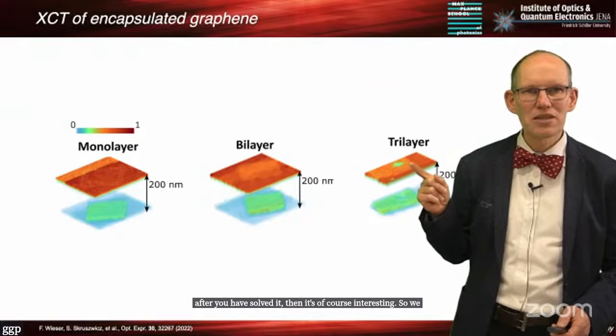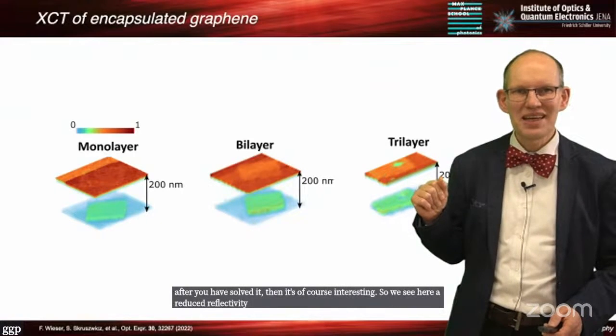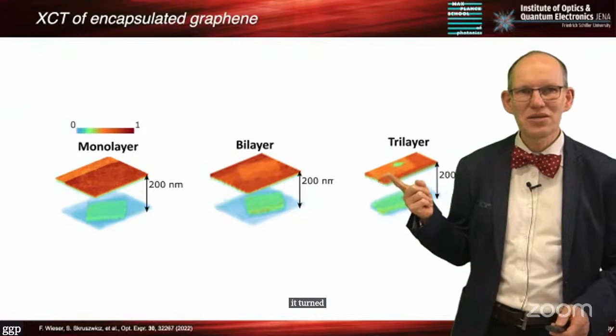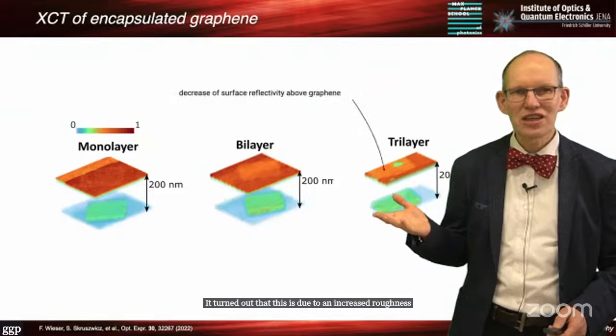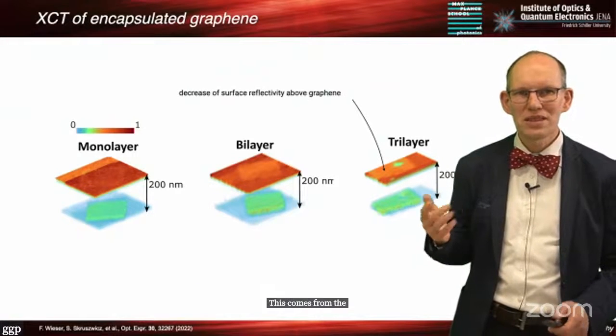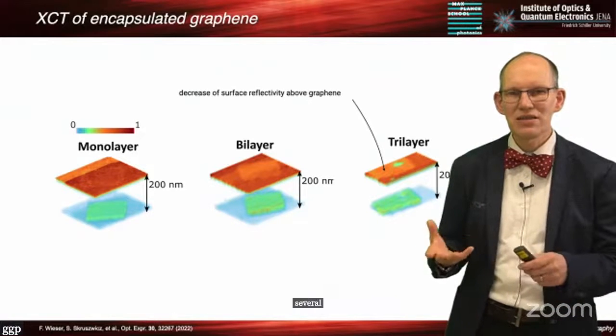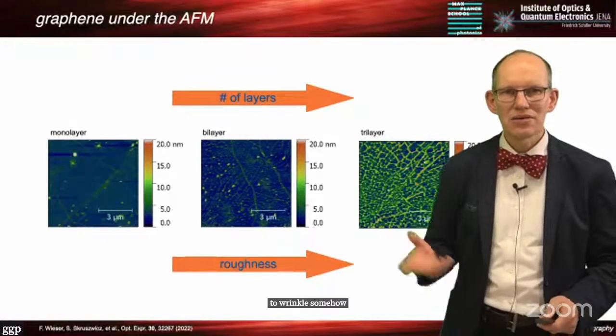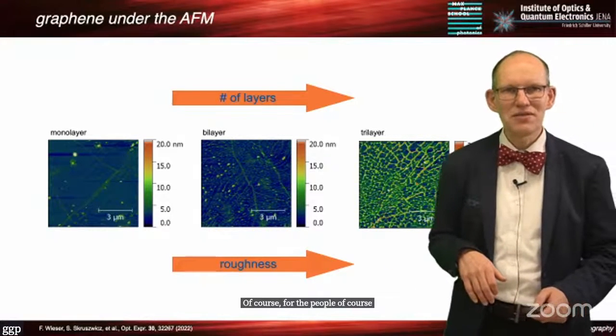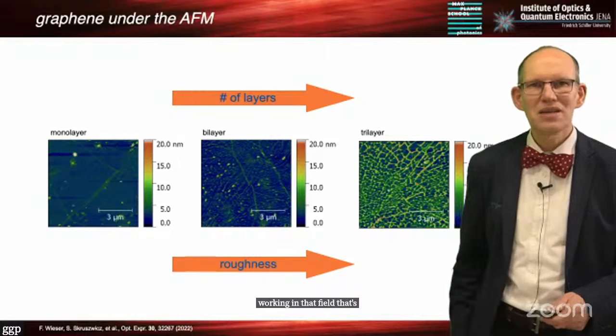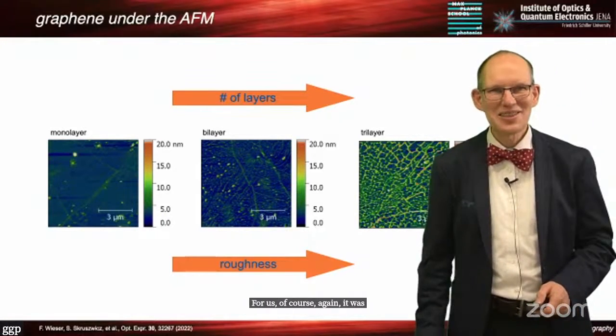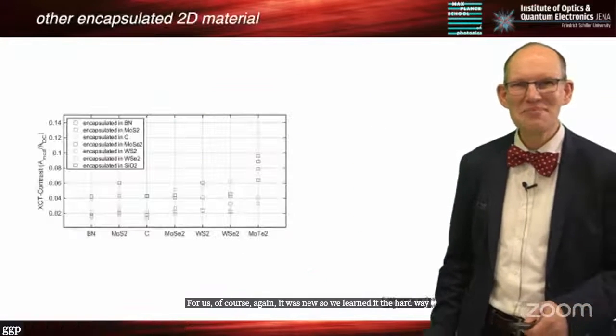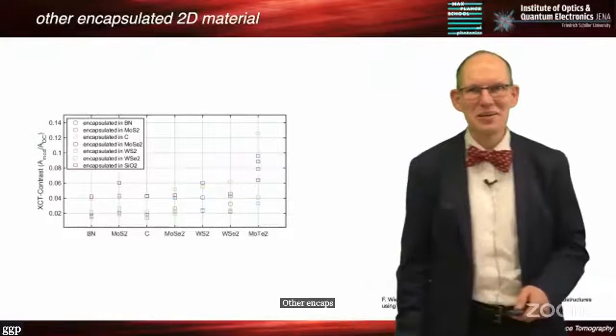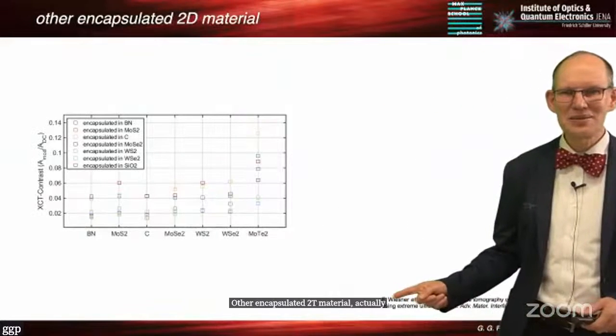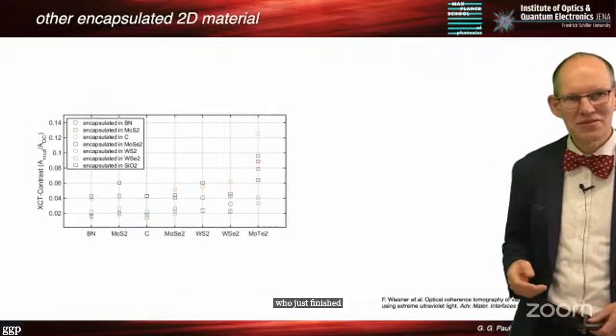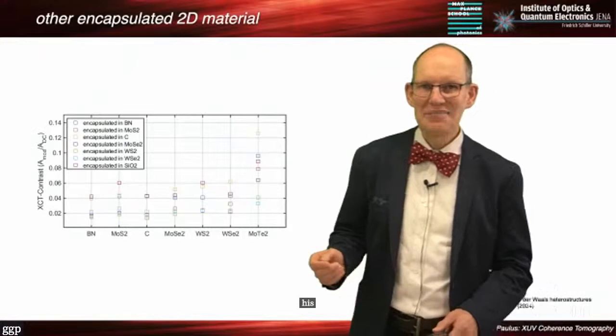So we see here a reduced reflectivity, right? It turned out that this is due to an increased roughness. And this increased roughness comes from the fact that if you stack several graphene layers, they tend to wrinkle somehow. Of course, for the people working in that field, that's known since a long time. For us, of course, again, it was new. So we learned it the hard way, as so many other things. Other encapsulated 2D material. Actually, my student Felix Wiesner, who just finished his PhD a few months ago, did a systematic study.